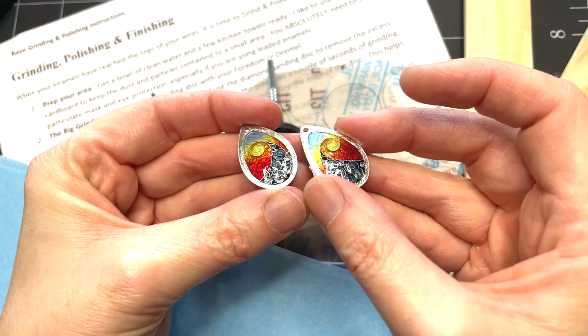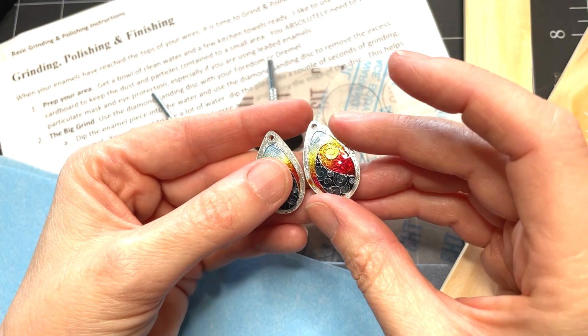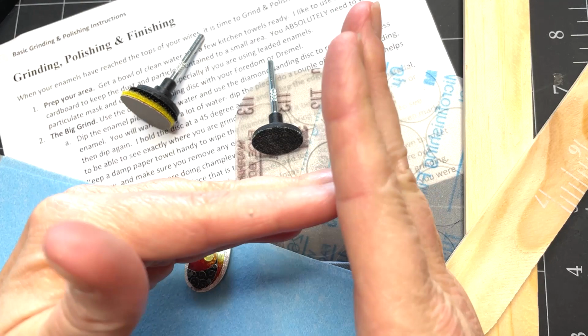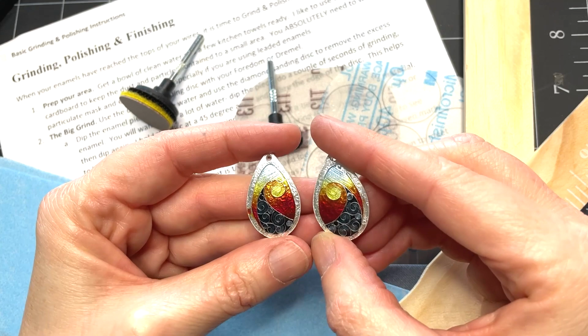If you see wires really kind of jutting out, you might run into problems in the first grinding pass. If the wires are really sticking out of the enamel, when you go to grind them, they might have a tendency to bend over and embed themselves into the glass, which gives you a fuzzy looking line, and it's harder to deal with.